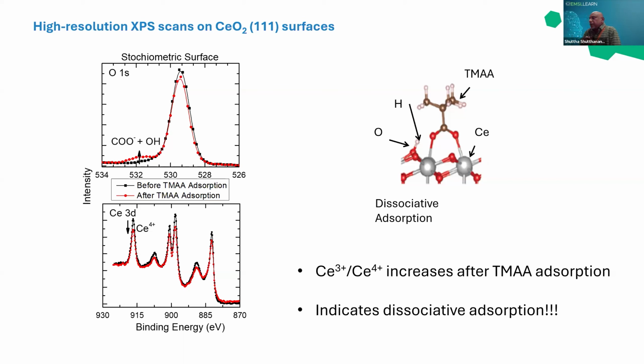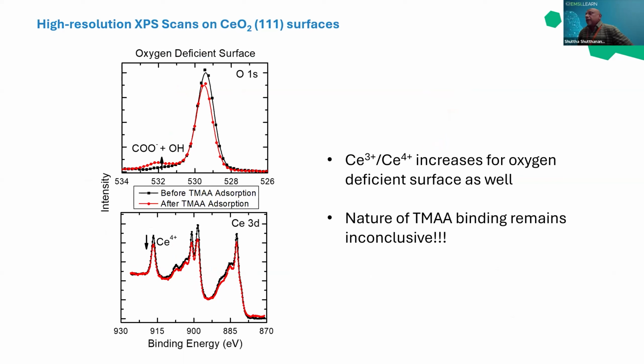So that is called, we call this dissociative adsorption. If you look at the, go ahead, next one, please. If you look at the reduced surface, you can clearly see the same difference, but the cerium 3 to cerium 4 ratio increases in this particular case.